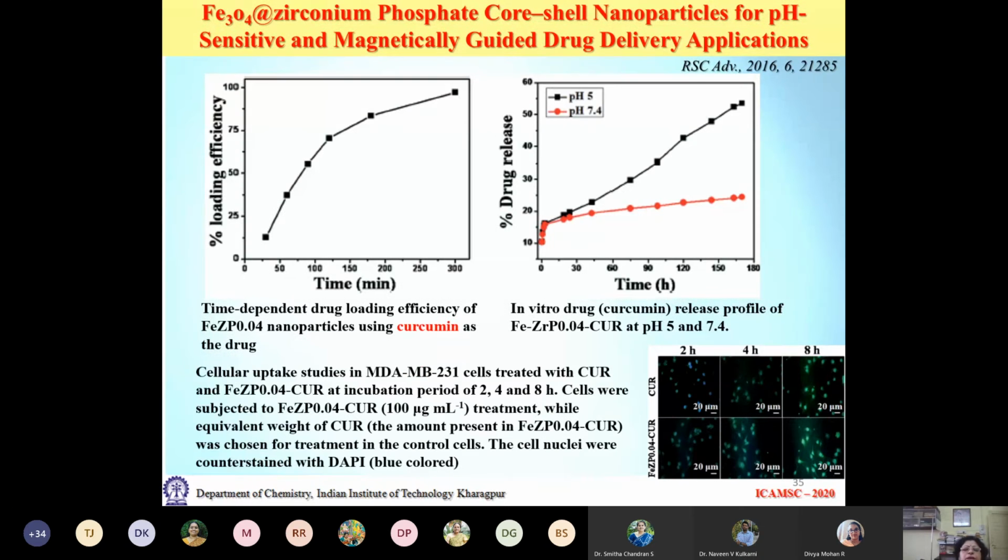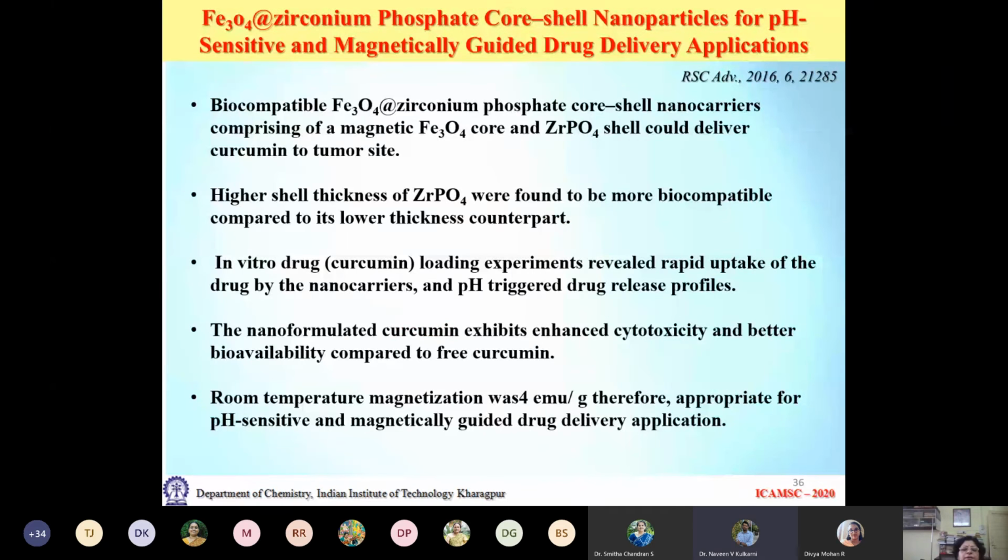I'm not going to go into the detailed profile. It is meaningless until you do it yourself. So obviously you have a magnetic material which is not very highly magnetic, because it is a superparamagnetic particle you have generated. The loop is not opening, so the magnetization is going to be low.